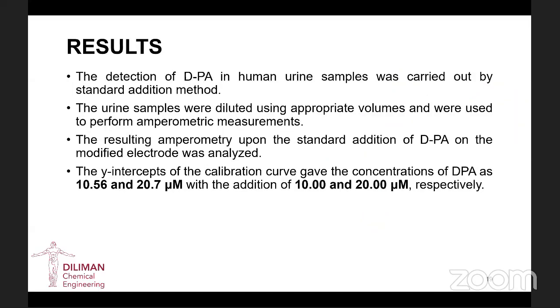And then afterwards, we used the electrodes in human urine samples by standard addition method, and we got values of 10.56 and 20.7 micromolar on average, with the addition of 10 and 20 micromolar DPA in the urine samples respectively. So the recovery range values are around 105%.